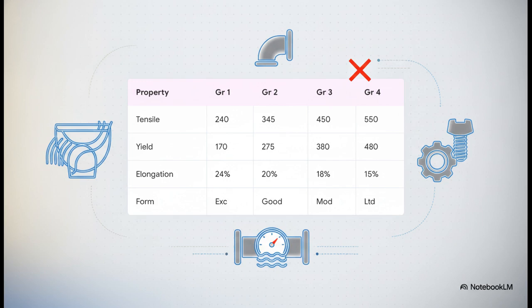Now look at the other extreme, Grade 4. It provides industrial-level purity and huge tensile strength at a minimum of 550 megapascals, great for high-strength fasteners and valve bodies, but its formability is quite limited. Grade 2? It hits the absolute sweet spot. High purity, a solid 345 megapascal minimum tensile strength, very good formability, and 20% minimum ductility. It is quite literally the optimal Goldilocks choice for things like seawater piping and pressure vessels.